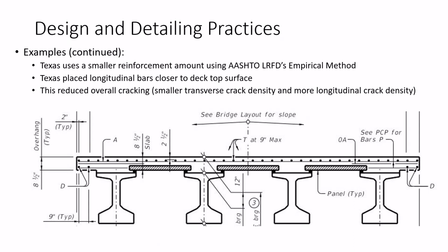The other change they made is that the very top layer of rebar, the layer closest to the top surface, is the longitudinal rebar. The reason is that their prevalent cracking was in the transverse direction, so the longitudinal rebars restrained those cracks better. They did help reduce overall cracking. So they got much smaller transverse cracking, but more longitudinal cracking. But overall, they did see a reduction in cracking, and they're happy with these changes.